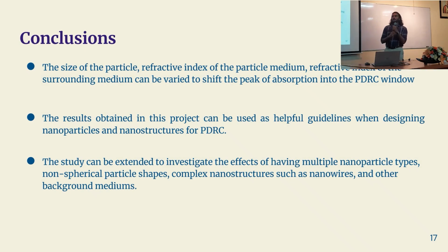At the end of my analysis, I concluded that we can indeed change the size of the particle and the refractive index of the material and the surrounding medium to vary the peak in the absorption cross section. And these results can be used as a guideline when synthesizing real materials.